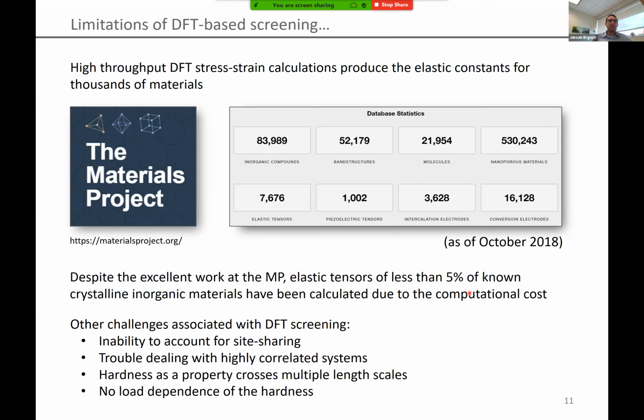So the ability to go through and calculate these at the first principles level is a good opportunity, but it's not ideal. As we thought about it further, there are other challenges with doing pure DFT screening—things like the inability to account for site sharing. You can do this with DFT, but it's not super straightforward in a high throughput format. There's also challenges dealing with highly correlated electronic systems. Again, it's possible with DFT, but it's not ideal, especially in a high throughput format.